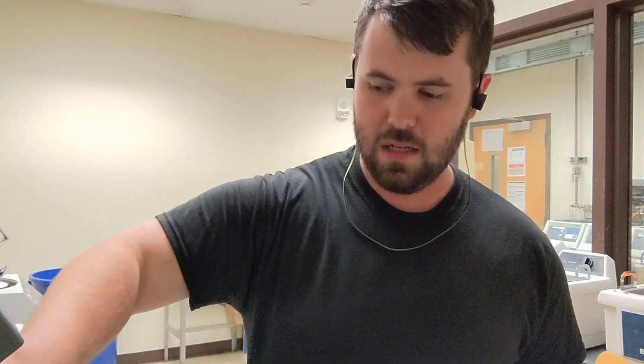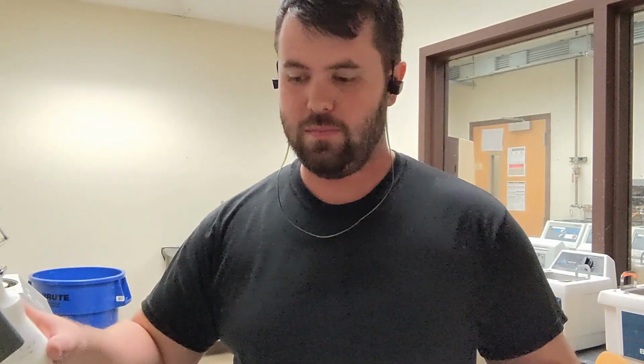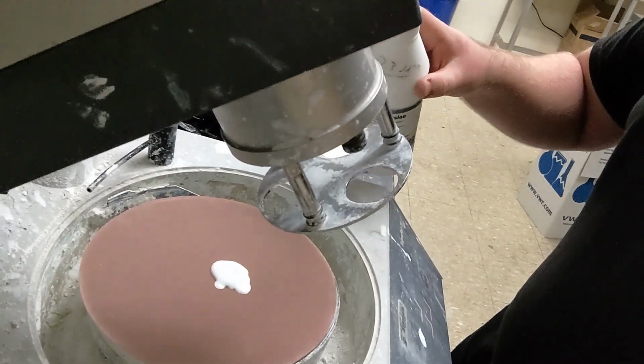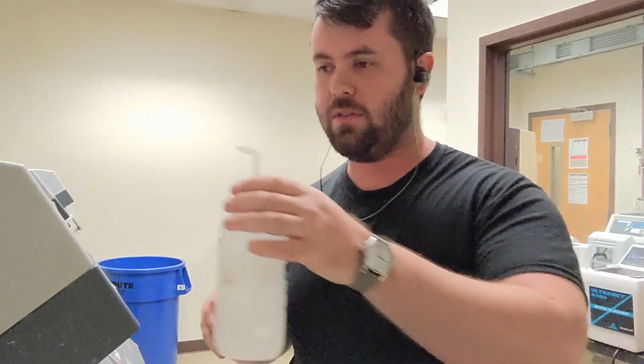And in reality, in order to get a good final polish, you need to just kind of pour on the stage, and you need about a little bit more than like a quarter size amount of polishing. So this white stuff here. And then throughout, instead of adding more polishing solution, we actually just add some distilled water, and that kind of evens it out and distributes and cleans our surface, kind of extends our polishing. So we need very, very little at the end. This is also the messiest last one because it's a little bit thicker than the other 2, so it likes to throw clumps around if you put too much, which a lot of people do. So anyway, 1 more step, and then we're all polished, and then we will go on to etching.